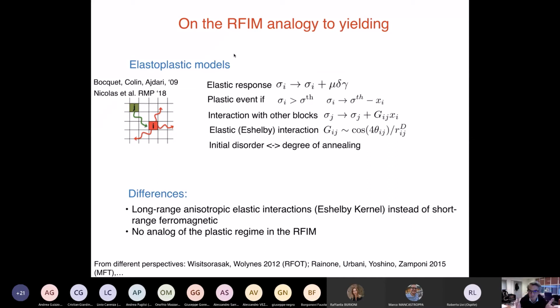This reminds me a lot of what happens in the hysteresis of the random field Ising model. In the random field Ising model, you have all the spins starting, let's say, down, because the initial value of H is negative. Then when you increase the value of H, maybe one spin has a local random field which is positive, and so it will be the first to flip. And when this flips, because of the interaction with the others, other spins will flip.